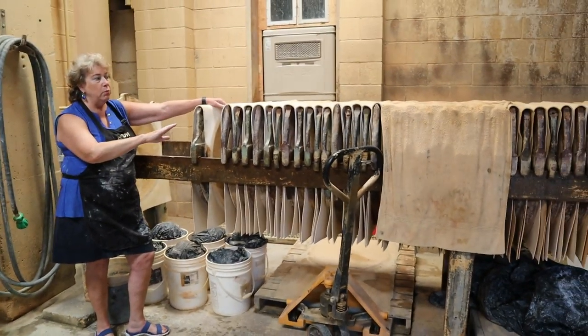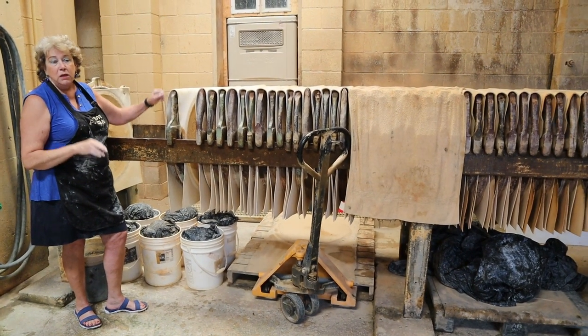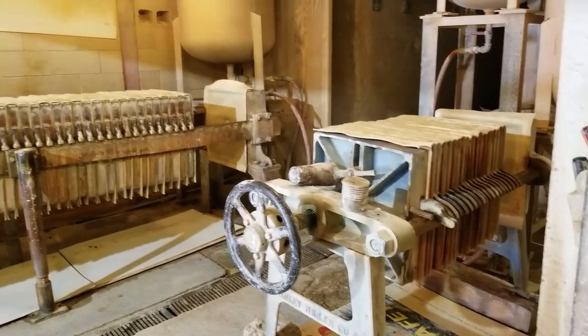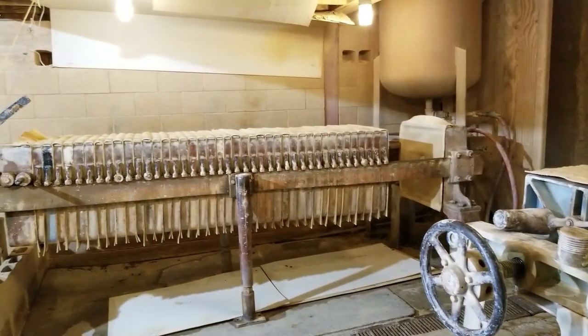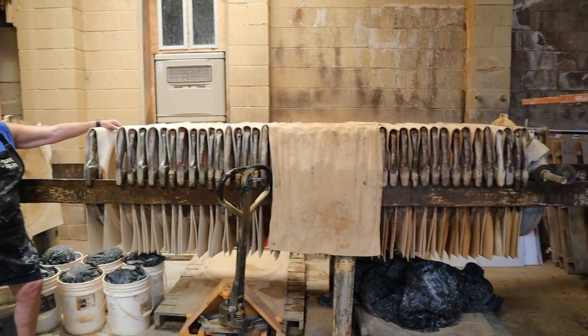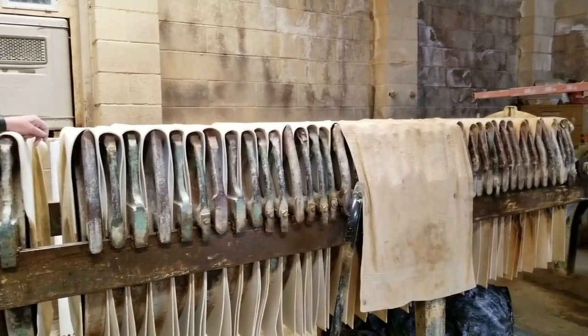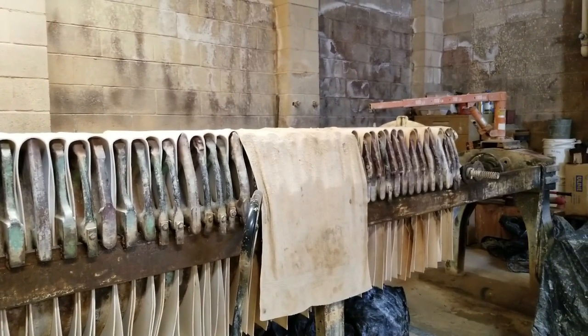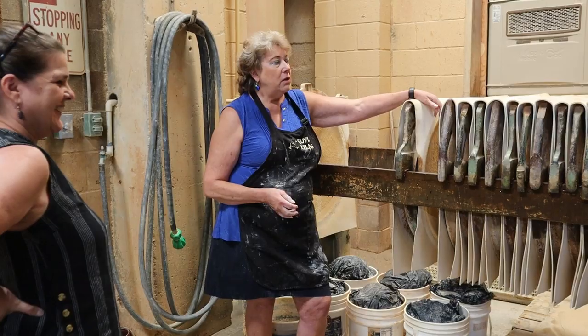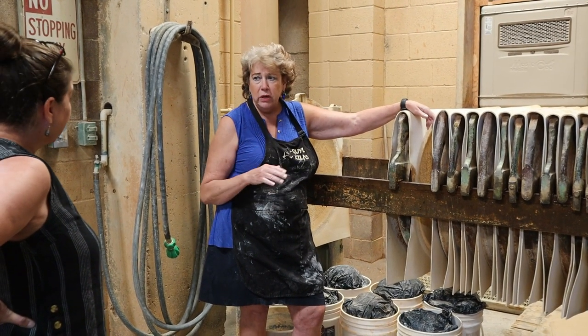Once we start pushing more clay water into the mix, the water that's in it perks through the felt. So we're pushing in 4,000 pounds of clay as a slip, compressing it to 2,000 pounds of clay as cakes that look like a big Eggo breakfast waffle. And then we're pushing out 2,000 pounds of water. We're borrowing water from our well, we're using it to mix, we're pushing it back through, we're filtering it, and we're returning it to the well. No harm, no foul, we're not adding anything that I don't want in my drinking water. So then the cakes from here are what will feed into the pug mill to slice and dice and extrude that as a block.